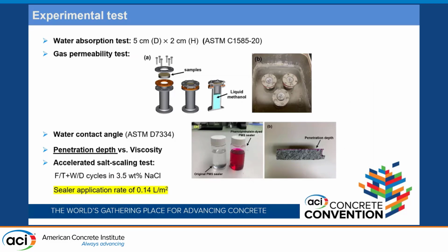Once we prepare our samples, then we start the water absorption test following ASTM, and test the gas permeability coefficient. In this study, we use liquid methanol as the gas source. We heat this device to accelerate the evaporation of this methanol. Then we can calculate the gas permeability coefficient based on the mass change during this process. Then we also test the water contact angle, the penetration depth, and the viscosity of these sealers. Finally, we run an accelerated salt-scaling test.